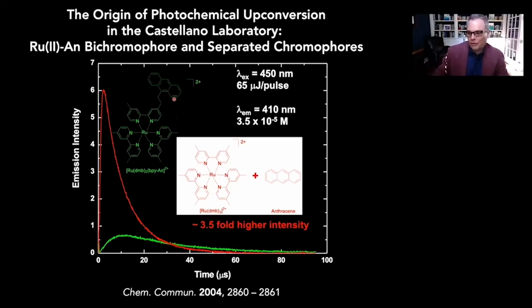This was the model system. Our compounds of interest were basically, could we excite it and do one energy transfer? Could we excite it with a lot of photons and do two energy transfers or three energy transfers within the same broad laser pulse? We were terming this at the time regenerative triplet sensitization, to really be able to make a lot of excited states on a single molecule. And we knew that would require high pulse energies.